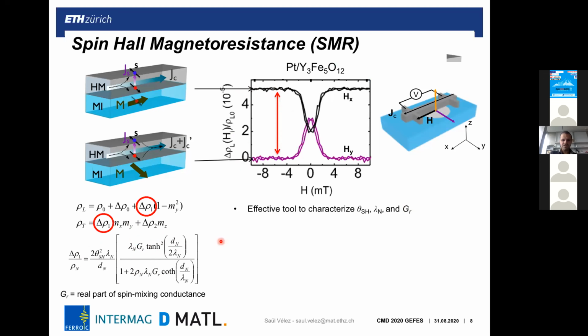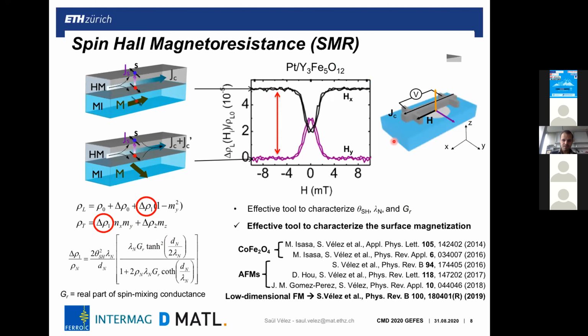Initially, this effect was used as a tool to characterize the spin transport properties and the interface quality of different heterostructures. But last but not least, we can also use this tool as a way to probe the surface magnetization of magnetic insulators. For instance, by tracking the field dependence, you can see at which magnetic field you have saturation, and how the resistance evolves will also give us information on whether you have, for instance, some paramagnetic contribution.